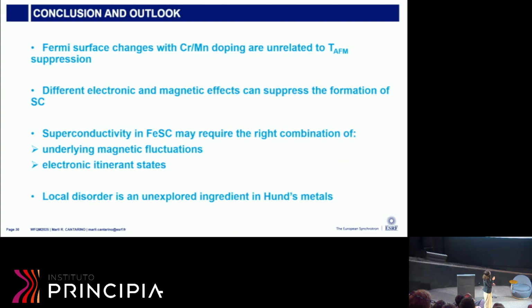So regardless of what is happening to the electronic structure, we have almost the same phase diagram in the low doping regions. Different electronic and magnetic effects can suppress the formation of superconductivity, so we have different behaviors and suppression for both samples, for both phase diagrams.